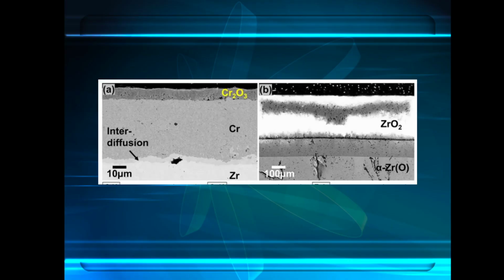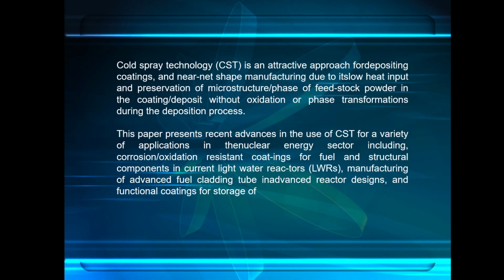Here is an example of the microstructure of oxidized chrome-coated zirconium alloy at 1030 degrees Celsius. The oxidation kinetics for the cold sprayed chromium coatings were comparable to those of bulk chromium samples, indicating that cold sprayed chromium coatings were very dense. At elevated temperatures, interdiffusion at the coating-substrate interface resulted in formation of a chromium-zirconium intermetallic compound layer, which exhibited diffusion controlled growth kinetics.